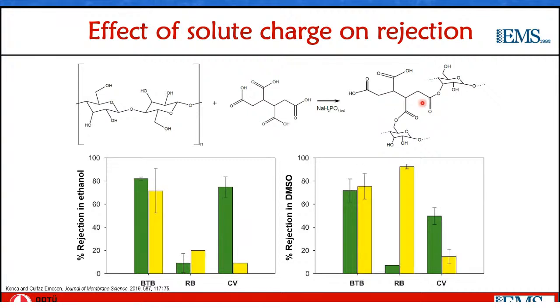Then when we did that and measured the rejections of the same three dyes in the two solvents, what we saw was that for the neutral dye, there was not much that changed, but for the charged dyes, and more pronounced in some cases, the rejection was reversed. So what was high became low, and what was very low became very high. This implies that electrostatic interactions between the solute and the membrane seem to be effective in the transport of the solutes. And what was also interesting to see is that, especially for the cases where the switch in rejection was most significant, we also saw